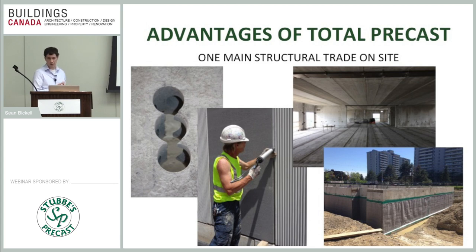We also take care of all core drilling — plumbing, mechanical, and electrical penetrations from two to six inches drilled on site. The key is knowing locations early. With total precast you need a mindset shift: get mechanical and electrical plans in earlier so we can locate and design for penetrations on our drawings. If we're not prepared, we may not have designed for an opening, which can be tricky — precast has a strand pattern running the length of the slab, and compromising the strand can cause failure. Any opening bigger than six inches can be manufactured during production by boxing out with a foam insert.